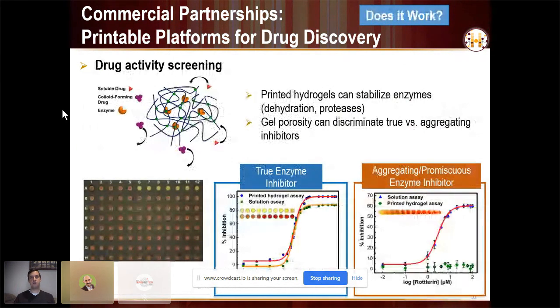So what we did is we printed an enzyme that was relevant to drug screening inside our hydrogels, and then we applied what was a known enzyme inhibitor, so something that was actually a drug for this enzyme, a true enzyme inhibitor that can actually bind, and also something that gave a positive result in a solution assay, but is a known promiscuous or aggregative inhibitor. What you can see in the solution assay in the bottom with the blue points, it looks like both of these work, right? It looks like both of these can actually inhibit the enzyme and both could be drug candidates.